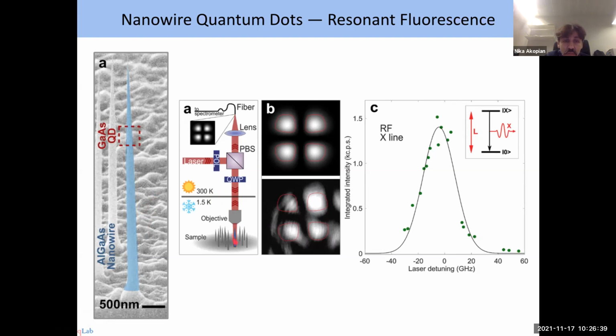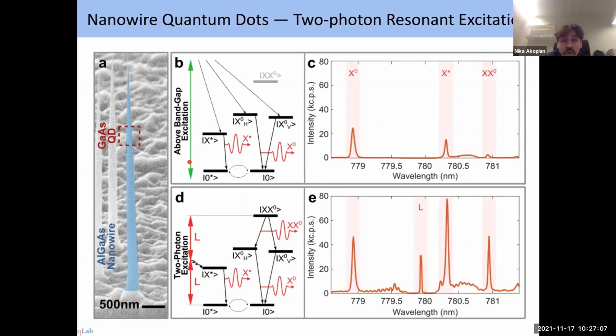And that's our setup. Nanowires are here, the objective here. That's a polarizing beam splitter. The laser comes with one polarization and excites a nanowire quantum dot, and the emission with another polarization goes and is collected here. So we are able to perform resonant fluorescence. This is an example of scanning a laser through a transition of an exciton in a quantum dot in a nanowire. Here is an example of two-photon excitation. So we can come with a laser in between the exciton line and the biexciton line. This is the exciton line, this is the biexciton line, and this is the laser. When the laser is in between, you can have two-photon absorption. Two photons from the laser have exactly the same energy as the biexciton, and then you can have a cascading emission from the biexciton to the exciton and to the ground state.